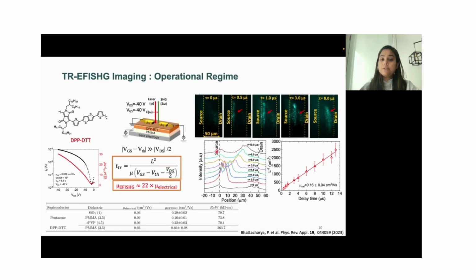And thus we see a little bit of SHG activity. However, the most interesting peaks in this case are the ones that correspond to the polarization wavefront that moves across the channel as we let the motion of the charge carriers happen over their entire transit time. On application of the Maxwell-Wagner model, the slope of the position square versus delay time then gives us a sense of the intrinsic carrier mobility of these devices free from contact resistance or interface trap state density.